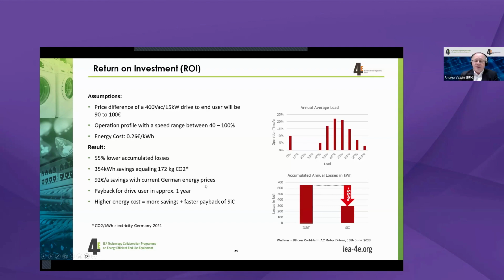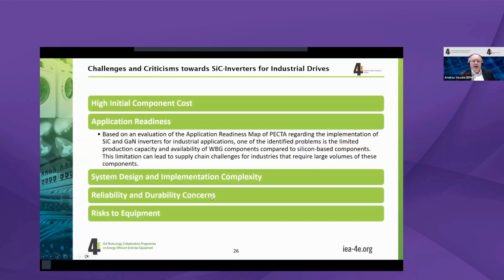Meaning, because especially in the part load range here, we have efficiency gains, we can then look at these gains and see what did we actually save. If you look at that, these 354 kilowatt hour savings multiplied with the 0.26 euros per kilowatt hour will give you then a payback in less than 1 year. On the other hand, looking at the initial component cost, it can be compensated by energy saving costs,